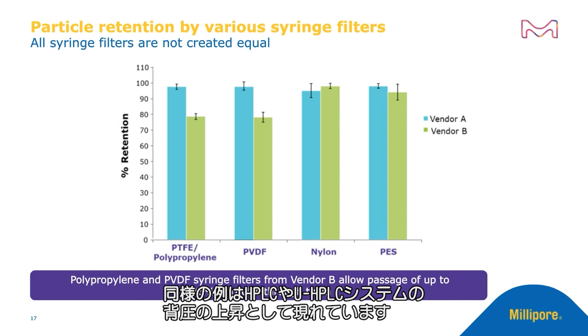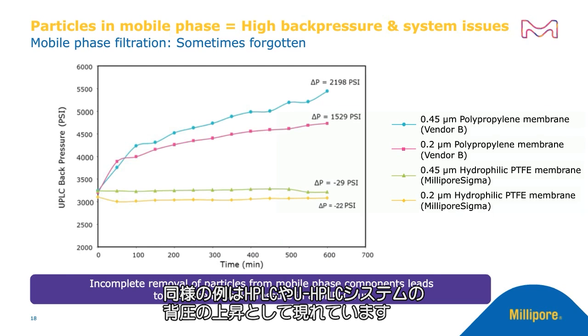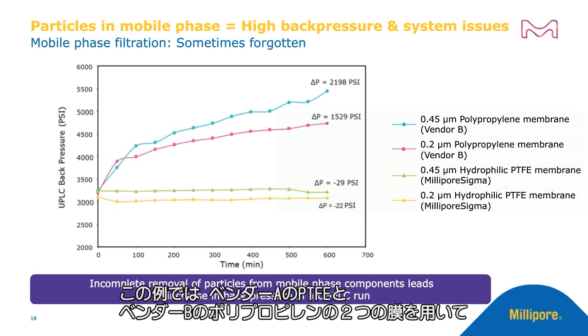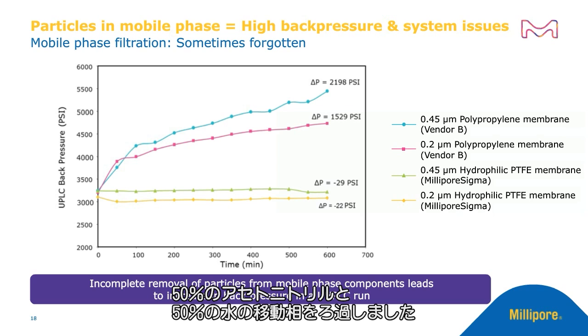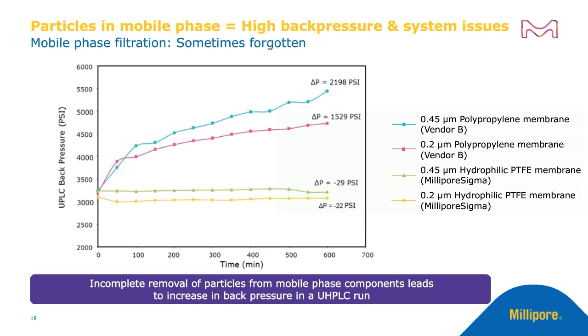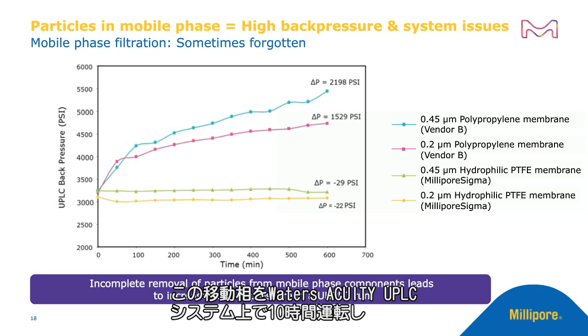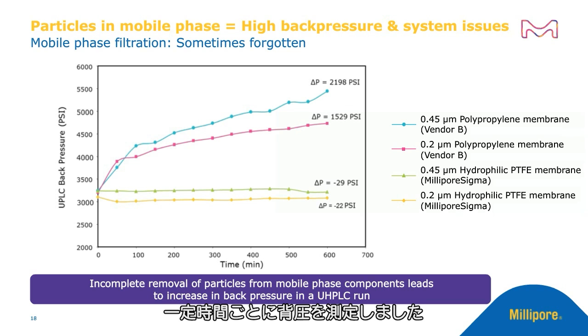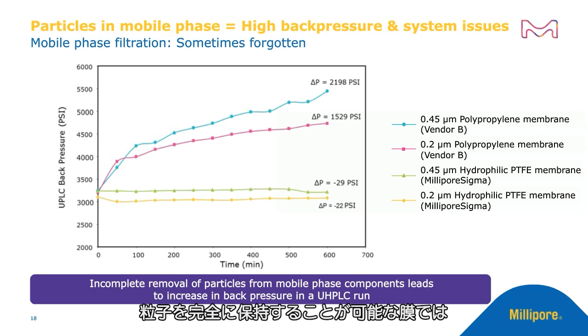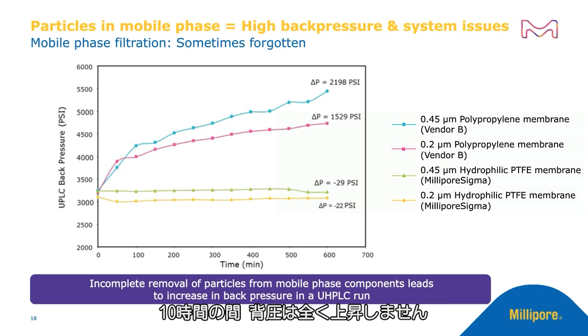The same example is now manifested by an increase in back pressure of an HPLC or a UHPLC system. In this example, what we did was we filtered a mobile phase consisting of 50% acetonitrile and 50% water using the same two membranes as shown in the previous slide, the PTFE from vendor A and the polypropylene from vendor B. This mobile phase was then run on a Waters Acquity UPLC system for a period of 10 hours, and the back pressure was measured every certain amount of time. As you can clearly see, for the membrane which allows for complete retention of particles, the back pressure does not go up at all over the 10-hour period.